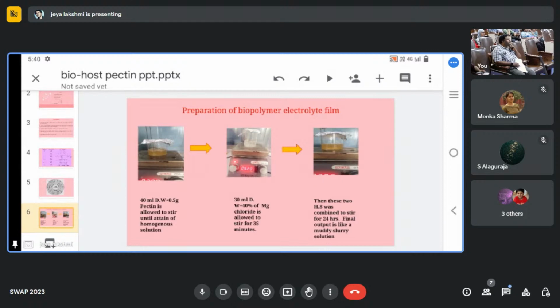And then next, I take 40% of the magnesium chloride and dissolve it in 30 ml distilled water for half an hour. And then I mix these two solutions into one beaker and allow it to stir for 1 day, depending upon the nature of the film, the nature of the biopolymers. It takes hours to dissolve, and after that the final solution is a muddy slurry.